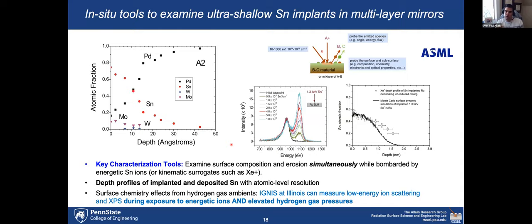But here's an example of how these in-situ tools ended up enabling us to decipher where the tin would go, what the fundamental mechanisms were, and how they evolved during the time scale of modification, to pinpoint how these tin particles not only contaminated the surface of the mirror, but if you were able to tune the plasma itself, you'd be able to self-clean the surfaces of these mirrors.